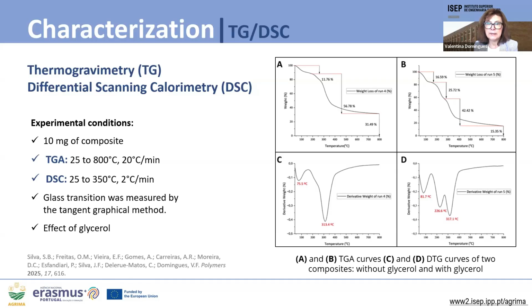Thermogram B shows an initial loss similar to A, the initial moisture loss at around 81 degrees. The main decomposition is slightly shifted to 317 degrees, indicating a minor stabilizing effect from glycerol. Also, thermogram A, from the biocomposite with only chestnut, has a higher ash residue at around 31% compared to B, suggesting glycerol facilitated a more complete combustion. All data of this work are described in this manuscript from Polymers.